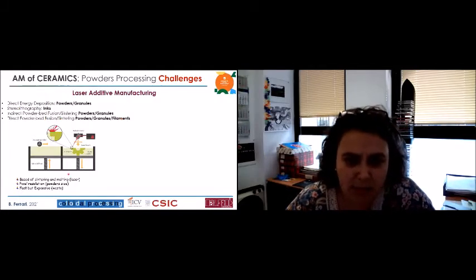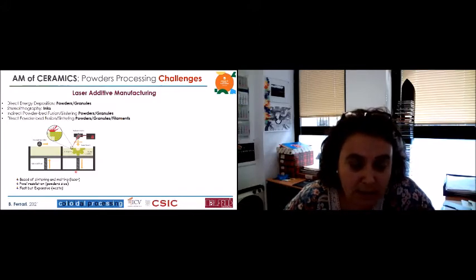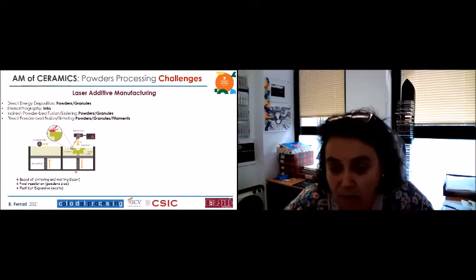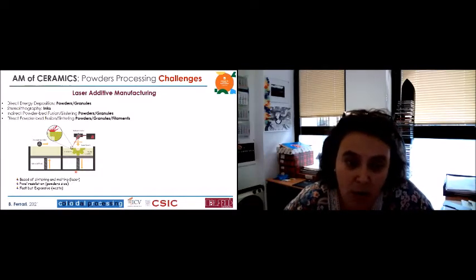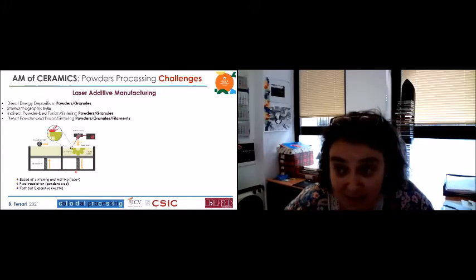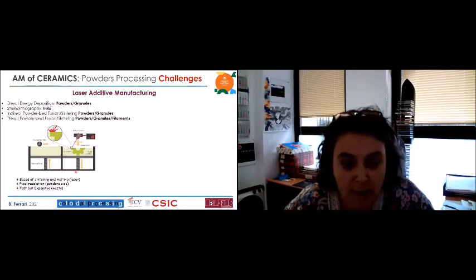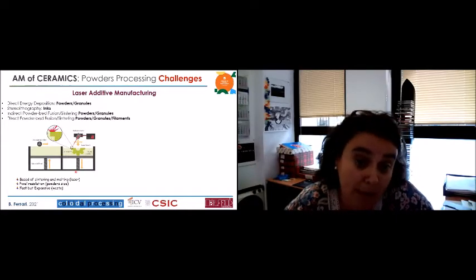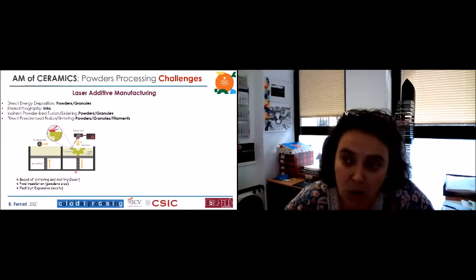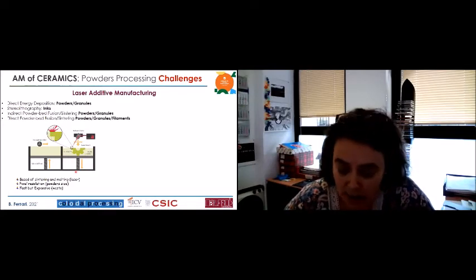What happens with this technology? These technologies are based on the sintering or melting of inorganic particles by the action of a laser. You can imagine that you are using light, so you have a pixel resolution, right? And it's a very fast technique to produce material, but it's very expensive. Why? It's very expensive because you use a bed of powder. That means you have a lot of waste of this material.